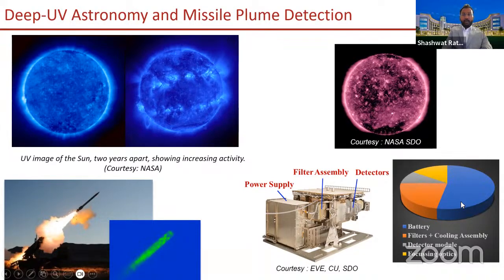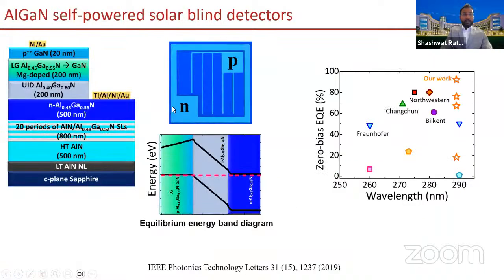So what if we could get rid of all these pies and only be left with this gray pie here? This was our idea, and we wanted to use ultra wide bandgap semiconductors because they don't need any filters and they don't need any focusing optics. And if we could make these self-powered, we could get rid of the battery completely. So we developed these self-powered solar blind detectors, which were engineered to have an electric field in the material even without applying any external bias.